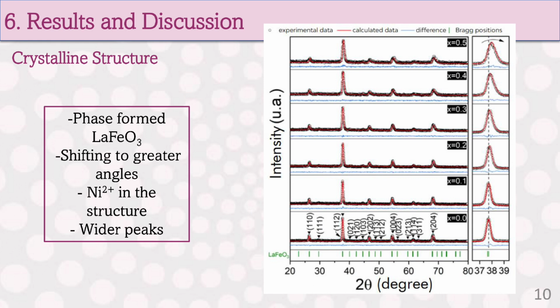The characterization performed by X-ray diffraction of the pellets obtained from the compaction and annealing heat treatment at 1073 K resulted in diffraction patterns that after applying the Rietveld refinement are shown in the figure, from which it was possible to identify the orthorhombic lanthanum ferrite phase with space group Pnma, for the undoped sample, proving that the stoichiometric calculations used were correct.